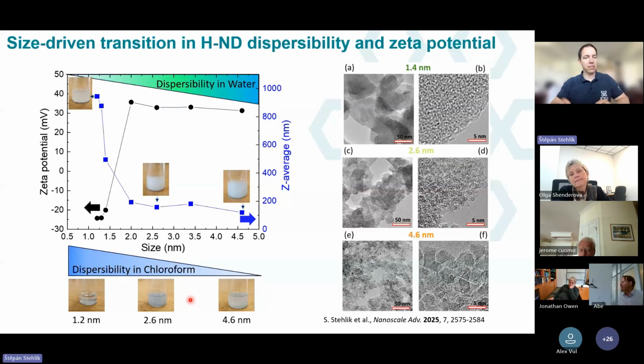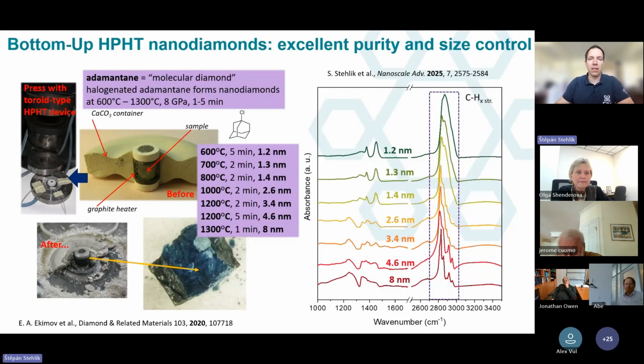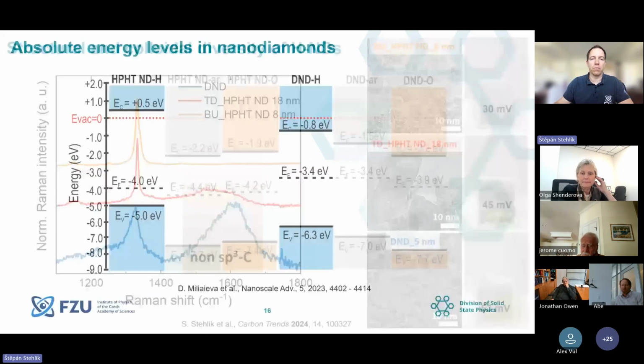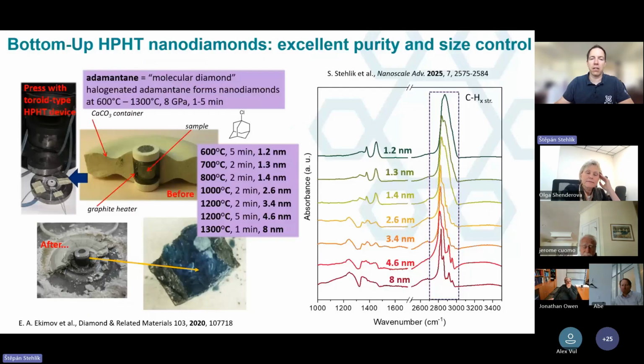That's maybe a bit of a misunderstanding, because maybe I mixed up a different source of the nanodiamonds. When we speak about this bottom-up HPHT nanodiamond, and maybe I will just go to my slide. Okay, so these bottom-up HPHT nanodiamonds are quite special, and if I show you the Raman spectra, you would see that there is no sp2 at all in this size range, right? This 1.3 nanometer is just an exception. There we saw some sp2, but it's probably connected with the formation mechanism. But in general, this bottom-up is a very specific type of nanodiamond. They really don't contain any sp2 surface carbon after the synthesis.